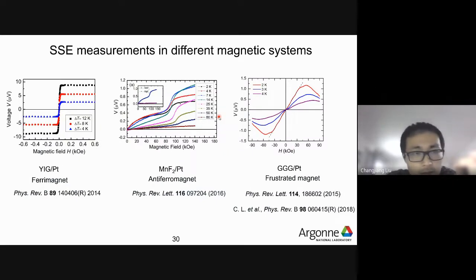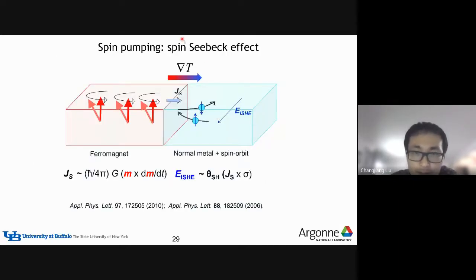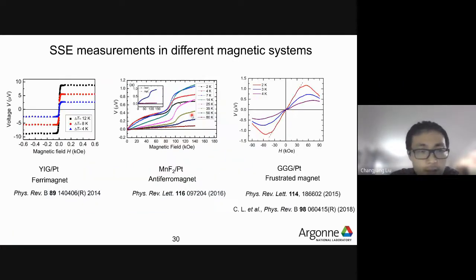So since its discovery, the spin-Seebeck effect or SSE, people have found that one can observe this effect in diverse materials. So let me remind you, in spin-Seebeck effect, we use a thermal excitation to excite a precession of magnons. In spin pumping, people use the microwave to excite a ferromagnetic resonance. Now, in spin-Seebeck effect, you use heat to generate magnons, and magnons can also produce a spin current flowing across the interface. So people have found that this SSE can be observed in diverse material systems.